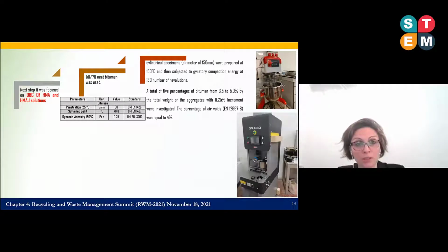The next step focused on the identification of the best bitumen content, that is the binder, of the hot mixtures. In particular, we used a neat 50/70 bitumen, whose properties are shown in the table on the slide. Specifically, we used cylindrical specimens with a diameter of 150 millimeters, prepared at 170 Celsius degrees under a gyratory compactor, as you can see on the right side. And we compacted specimens at 180 number of revolutions to reach desired properties, such as, for example, thickness, air voids contents, and density, in line with a specific tender specification.